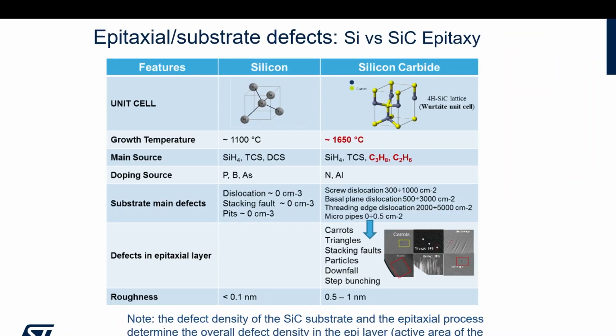Talking about defects, this is a comparison side by side of silicon and silicon carbide. Of course, 0 defects in the main substrate, 0 defects in the epitaxial layer for silicon. Silicon carbide has dislocations, basal plane dislocations, a lot of dislocations in the bulk. Whatever you do, you can reduce this concentration, but cannot go to 0. And then when you go to the epi, even with the best epi process, you still have some transfer of these defects, or some transformation of the defects of the substrate, that generates defects in the epitaxial layer and then in the active area of the device. They are called carrot, triangle, stacking fault, whatever.